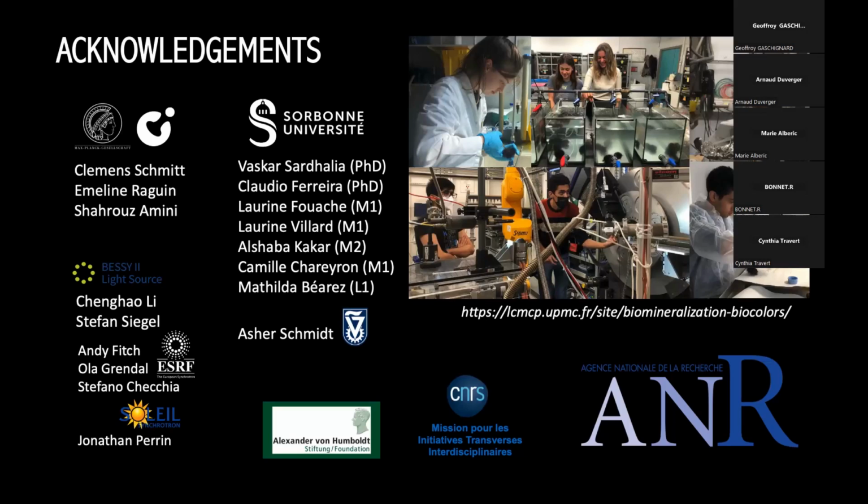So quite little. We're trying to fit what is happening in vivo. In vivo, we have about 1% weight percent of organics, and altogether, because it's not only pigments, it's also proteins and polysaccharides. Of pigments, we have much lower, like 0.1, let's say maximum weight percent. So we try to work at low concentration, but this is what has also been used for amino acids, for example, with the same concentration, and still they could show some lattice distortion.